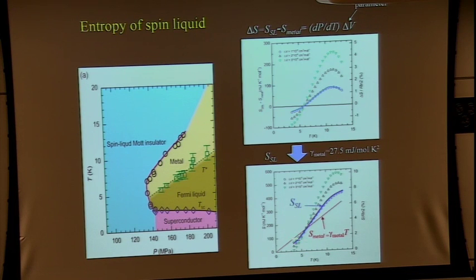Some rather steep increase occurs. So something happens here. But to obtain the entropies, we have to know the difference of the volume, delta V. But we don't know delta V. So delta V is a parameter, and we calculated the entropy for several values of delta V. It's difficult to see: 1, 2, 3, and 10 to the minus 8 something. But if we assume 3 for delta V, the resultant spin entropy shows a peak. This is unphysical.